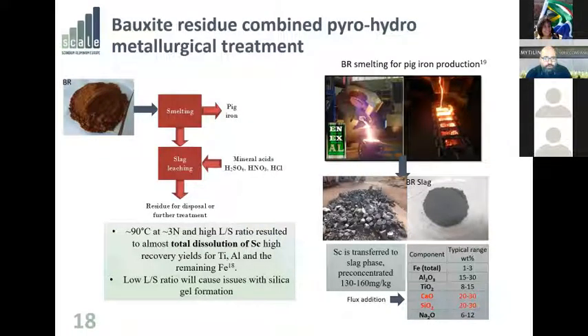So here you can get the total dissolution of scandium if you go above 3 N, and you will also leach out titanium and aluminum along with any iron that's remaining there. You have to be careful, however. A big problem in these phases is the formation of silica gel, especially if you go for a low liquid to solid ratio, you may end up experiencing silica gel formation. So this is a problem.